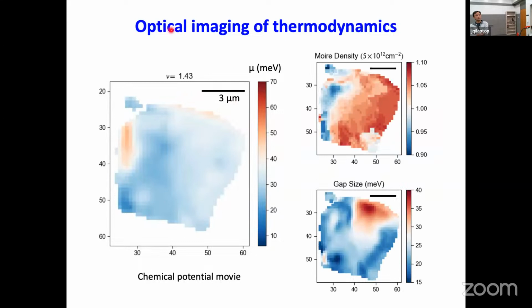And from this map, we can also try to extract the disorder in the Moiré density, which is about 10% variation in the system, as well as the gap size. Actually, the gap size will vary quite a lot more, it's way more sensitive compared to the Moiré density. So you change the Moiré density a little bit, the gap size actually can change a lot.